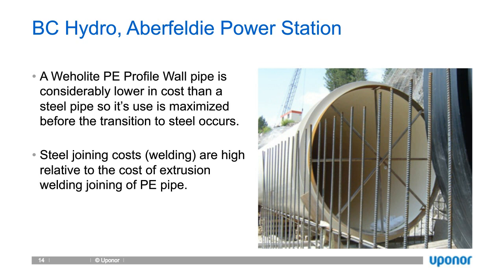And in fact, for steel pipelines, there's often a post-weld heat treatment at the joint to try to return the chemistry in the joint to more closely resemble the rest of the pipe.